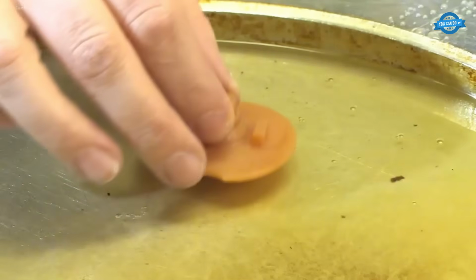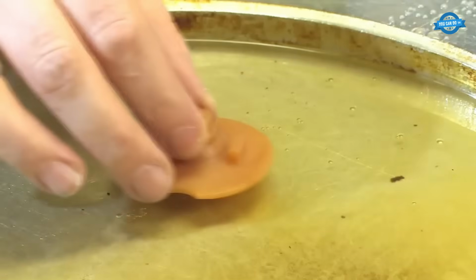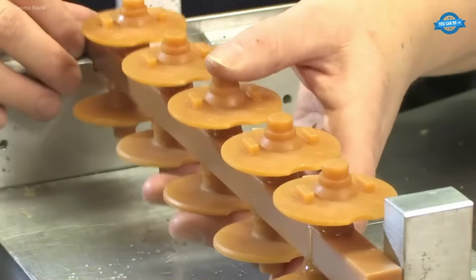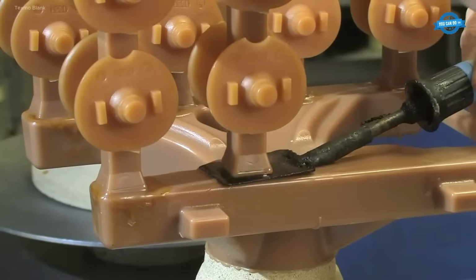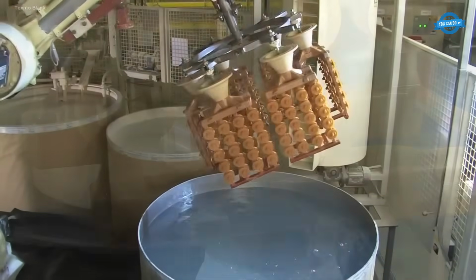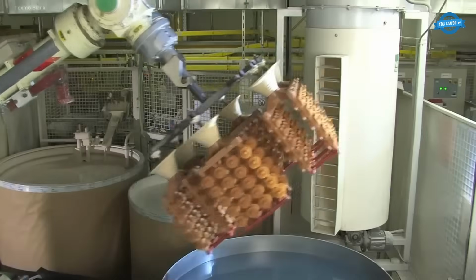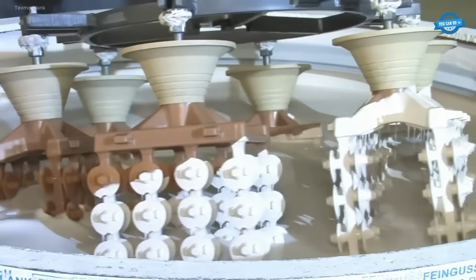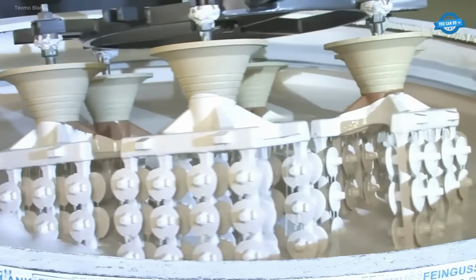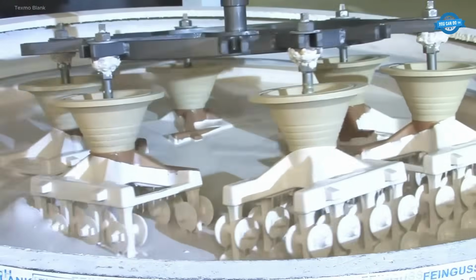The ceramic shells are then fired at around 1050 degrees Celsius to harden and stabilize the mold. Molten metal is poured into the hot ceramic mold using vacuum or low-pressure casting methods, which minimizes gas entrapment and defects, ensuring excellent metal integrity.